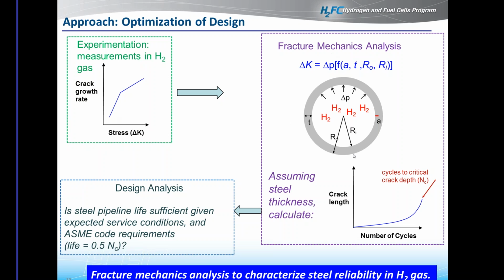So in other words, if we have a pipe and we know that we want to move a certain volume through it, that dictates a little bit of the radius. We assume we have an initial flaw, which is identified here as A. We can then use these experimentally measured fatigue crack growth curves and essentially get a fatigue life of the pipe.